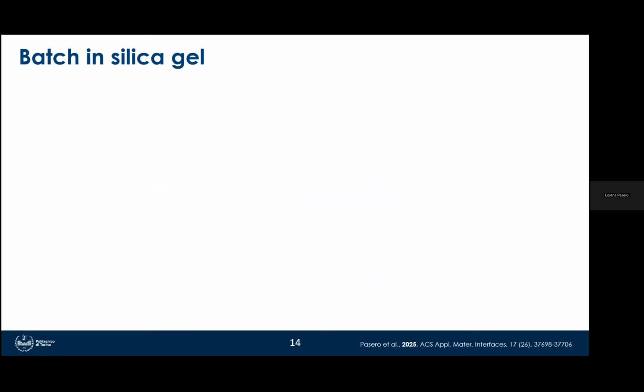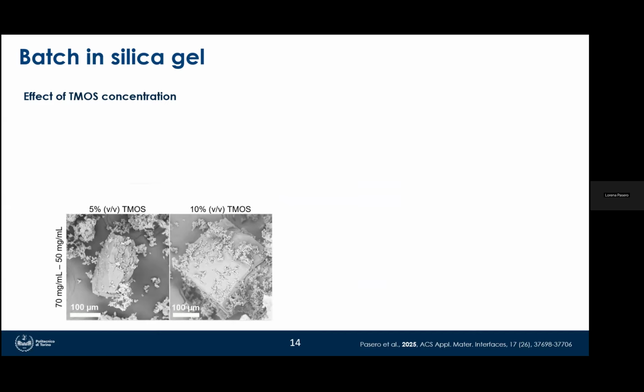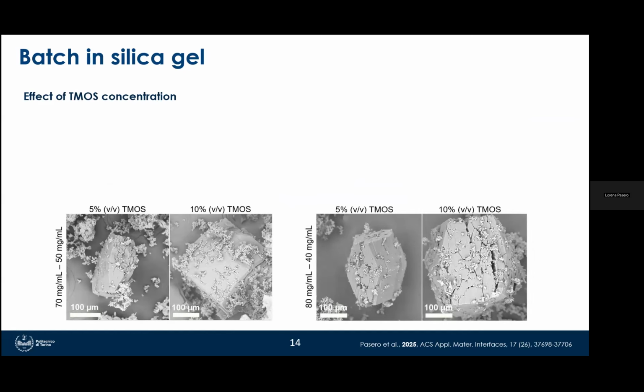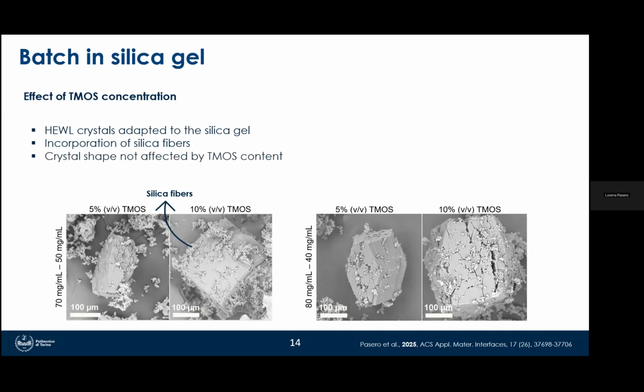The effect of the concentration of silica was also observed through scanning electron microscopy. So crystals were lyophilized, and then their morphology was evaluated through SEM. And we observed that lysozyme crystals adapted to the silica-gel environment, and incorporated silica fibers. Moreover, the concentration of TMOS did not affect the crystal shape, which appeared to be tetragonal, and this is coherent with literature, with the known form of lysozyme.